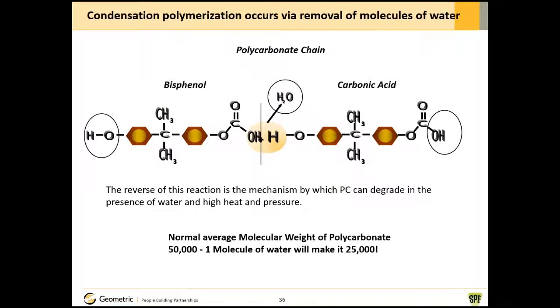Let's take the example of polycarbonate. Polycarbonate is the reaction of bisphenol A, the villain that we hear about, BPA. Not a villain in my opinion, but anyway, the villain BPA, bisphenol A, and carbonic acid. And in the reaction, a hydroxyl group and a hydrogen atom is expelled from these two molecules, and they combine to become a longer and longer chain. And this reaction continues till the average molecular weight of the chain, in the case of polycarbonate, is about 50,000.